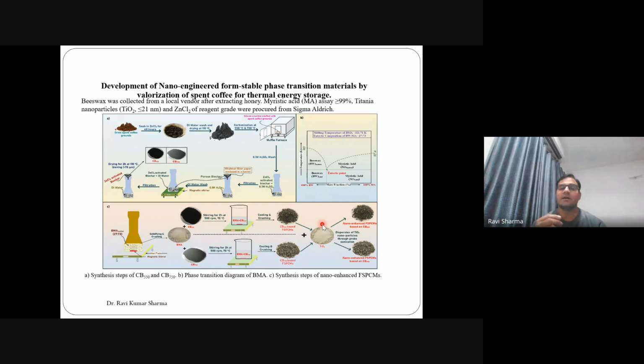Coffee seeds - after preparing coffee, we just throw away the seeds. So we collected those coffee seeds and did pyrolysis, converting them into biochar, then activated the biochar for more surface area of those pores. Then one PCM, myristic acid, was added into it for enhancing thermal conductivity further, and nanoparticles were also added. It's a complex procedure which is very difficult to explain here, and it will take a lot of time if I keep explaining it.